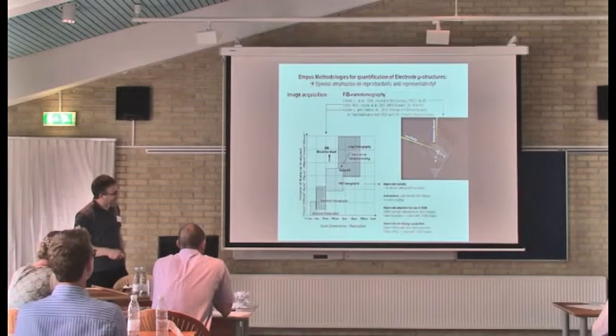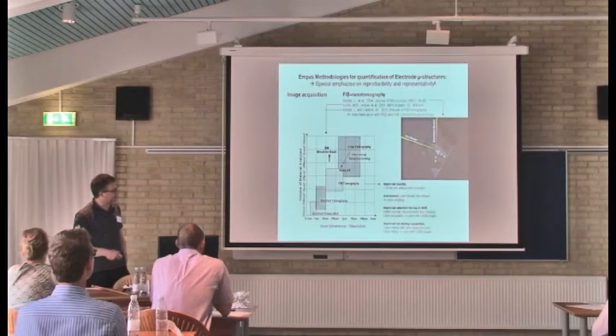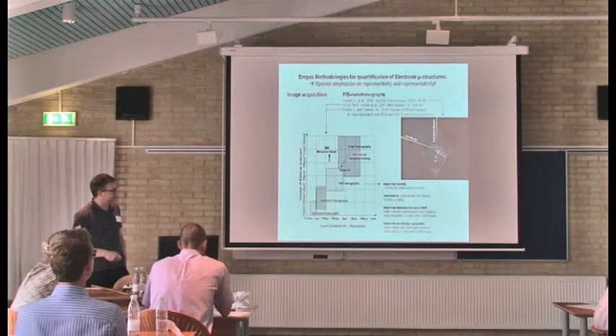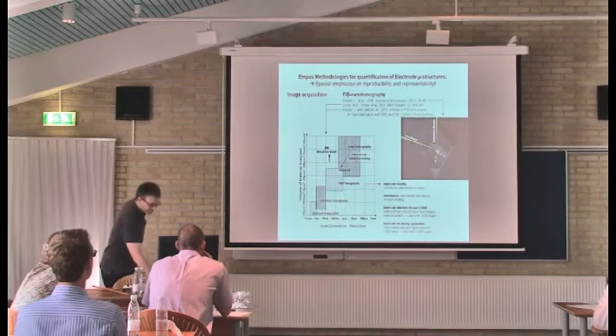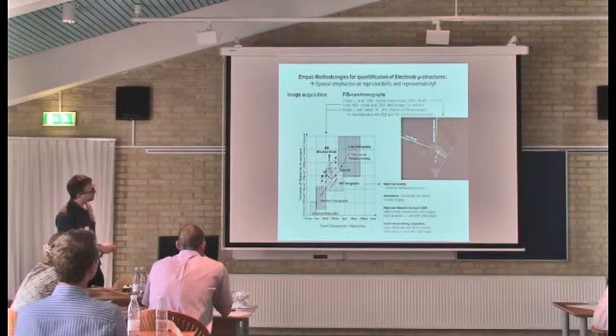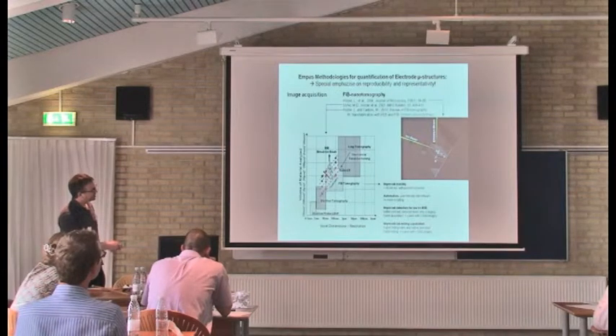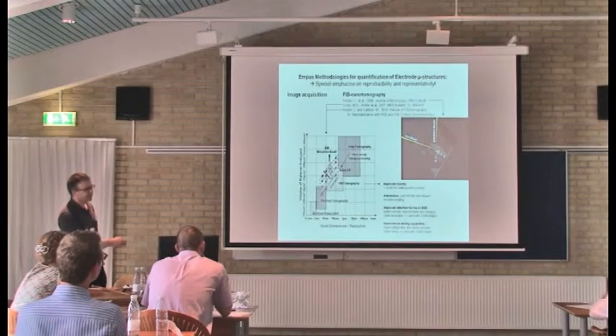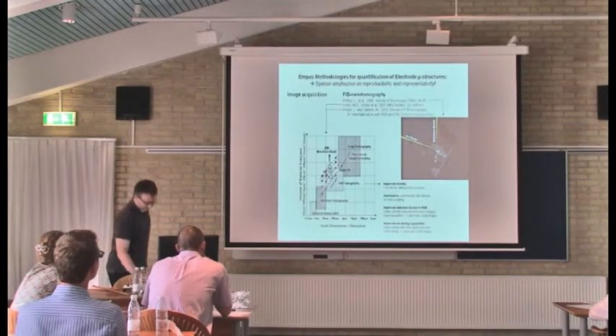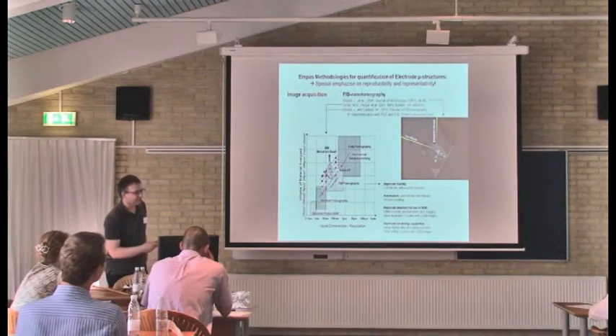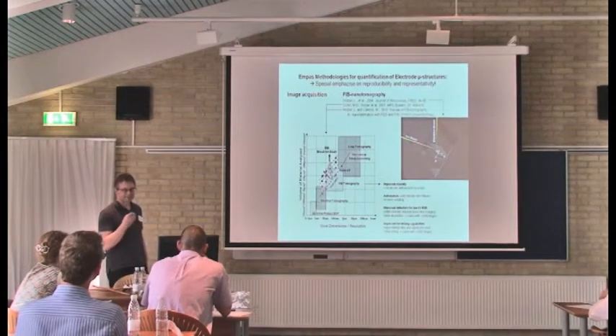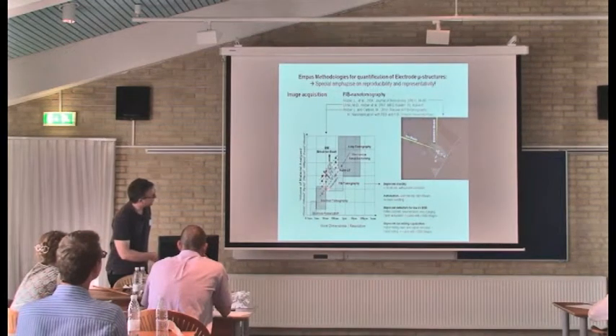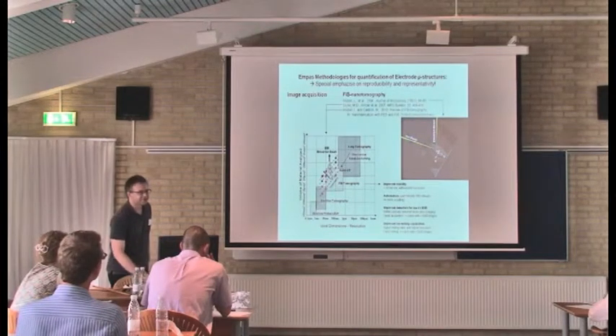With the ion beam, the milling capabilities are better to go to higher precision at higher milling rates, which also allows us to do larger cubes. FIB tomography developed from cubes with hundreds of images up to thousands of images. This is important because with 3D imaging, getting representative analysis is very important. Maintaining good resolution but analyzing larger volumes is really important.